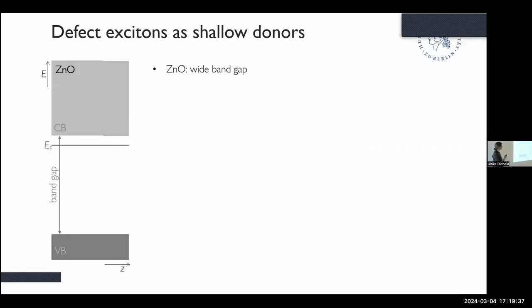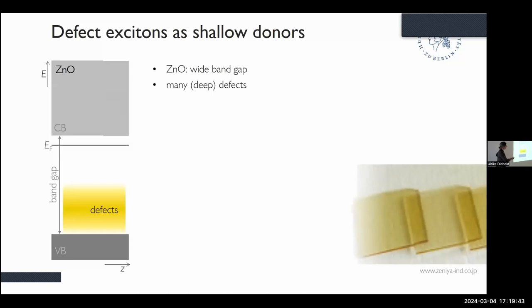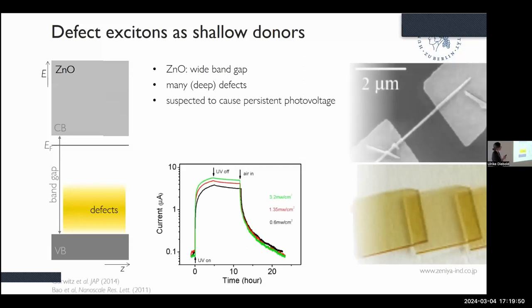Okay, so zinc oxide, it has a wide band gap, I already said so, but it also has many defects. This is why it's so yellow. And I mean, there are experts in the room on zinc oxide. One important aspect of zinc oxide is that it exhibits persistent photoconductivity. So when you shine UV light onto zinc oxide and you measure the conductivity through a zinc oxide wire, you will see that the UV light enhances the conductivity significantly, by almost two orders of magnitude. And then you turn off the UV light and the conductivity persists. And that is a puzzling observation.